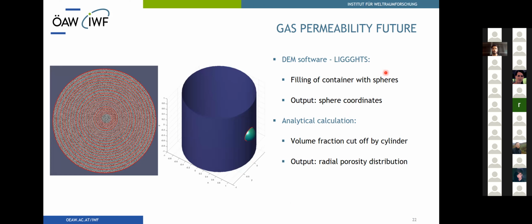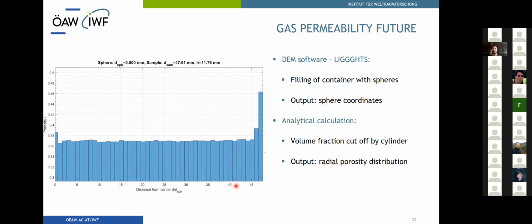The output of the simulation is the position and size of each sphere. We then divide the sample into arbitrarily small sections like the rings of a tree. After having established a method to efficiently and analytically calculate the volume fractions of all spheres that intersect the cylindrical segments, we can finally compute the radial porosity distribution. This example visualizes the effect of a boundary layer of increased porosity.